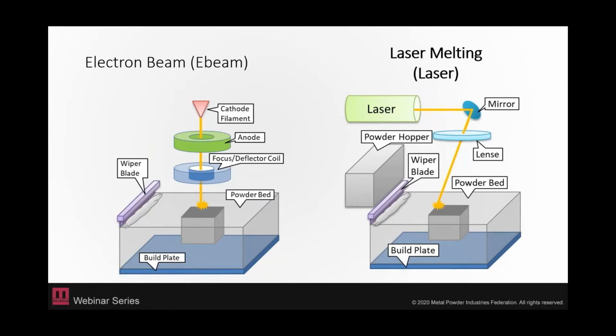But just in general, powder quality is the number one factor that's going to affect the quality of your printed part, as Emma has mentioned, and there's also a lot of literature coming out about this. And at ORNL, we actually did a study that directly linked the porosity of the final printed parts to the atomization process that was used to make the powder. And just as a hint, the more expensive the process, the less porosity was in the powder. So that just really showed us it doesn't really matter how fancy or complex your laser powder bed or your electron beam powder bed system is. If you have low quality powder, you're going to have a low quality part.